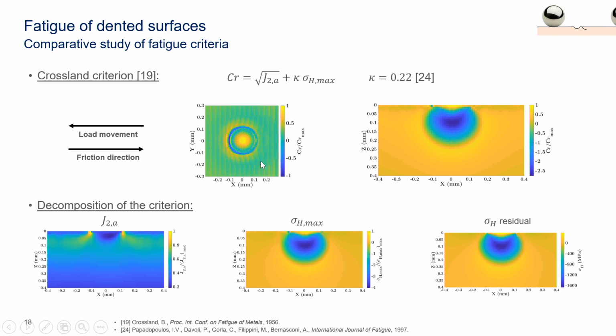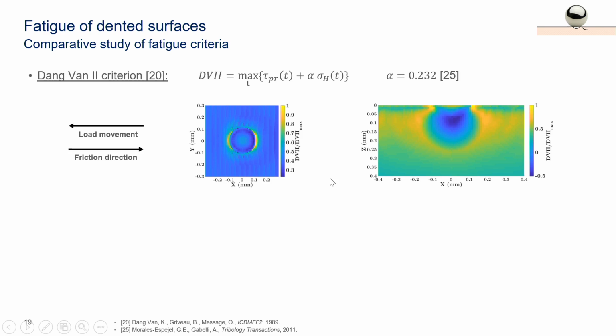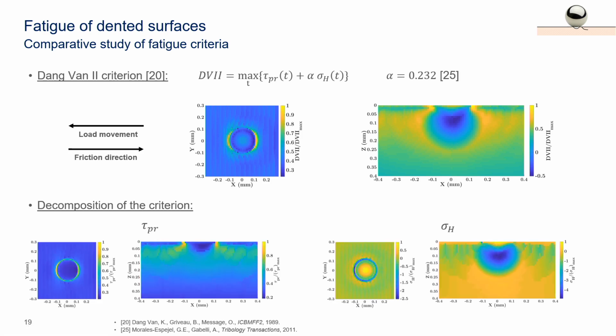For example, you can see here that this is blue. Blue, you are far below the criterion, then there is no damage normally, and there is some damage at the bottom. Then this is strange. This is not what we observe. Then maybe this is due to this parameter. This parameter comes from the literature, but okay. First one. Now the Dang Van criterion.